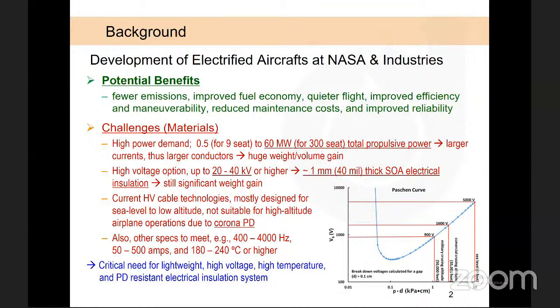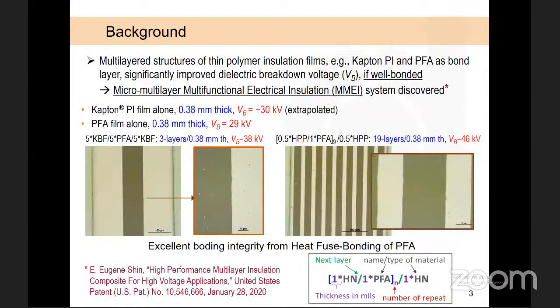In addition, the system should also meet high frequency and high temperature requirements. Therefore, developing a lightweight but high voltage, high temperature, and corona resistant insulation system was critically needed. Since we started our first project a few years ago, we discovered that multi-layered structures of thin polymer insulation films significantly improved the dielectric strength if they were well bonded.